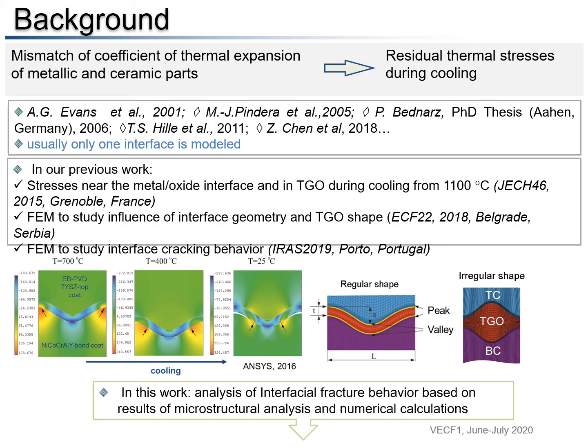The main cause of poor mechanical behavior of TGO is the mismatch of coefficient of thermal expansion of metallic and ceramic parts. The residual thermal stresses arise during cooling stage of thermal cycle, and they are of primary importance as their magnitude and distribution govern the durability of coating system.